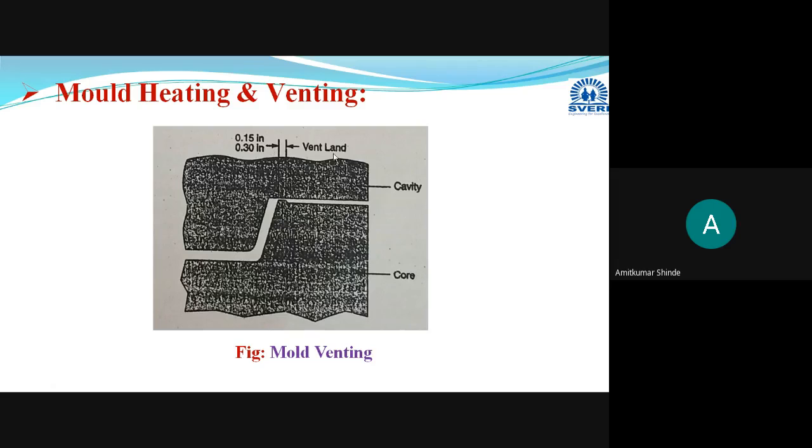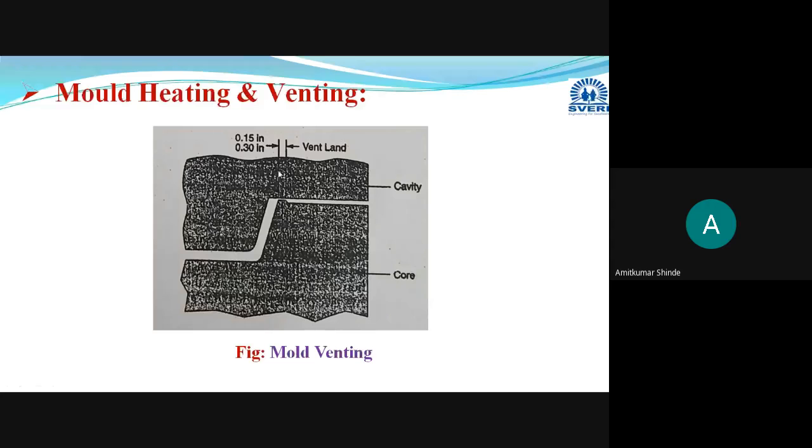And it is recommended that whichever mold, suppose you have provided some depth, 0.013 millimeter, then throughout that length it should be polished. Throughout that length it should be polished. These are recommendations related to mold venting. So these are general guidelines related to mold venting.